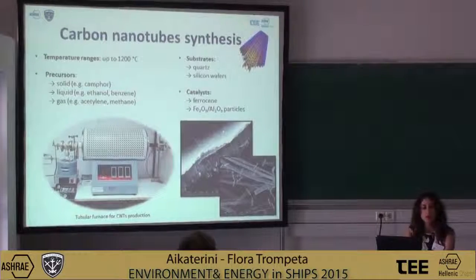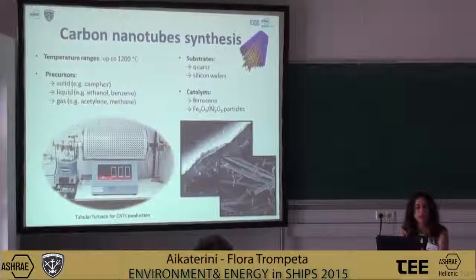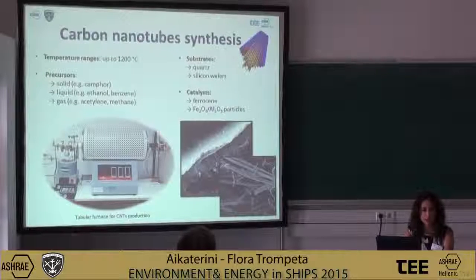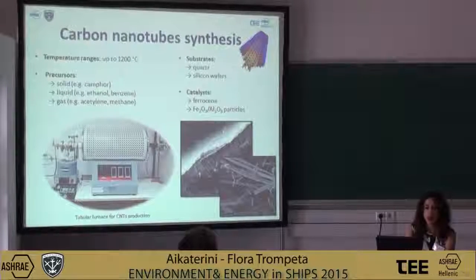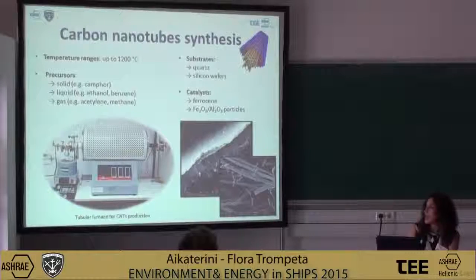The carbon nanotubes were produced in our study through the chemical vapor deposition method. It is a method that we use a tubular furnace that can raise temperature up to 1,200 degrees. As precursors, they can be used solids, liquids, or gases. And in our case, we used as a solid precursor camphor in combination with ferrocene, that is the appropriate catalyst. The CNTs can be grown up on quartz or silicon wafers. At the SEM image, we can see the produced CNTs that are synthesized in a structure of carpet, and in higher magnifications, we can see that CNTs are like small wires, like a small spaghetti.